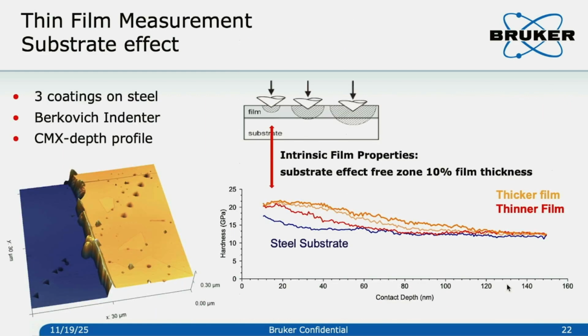So this is very important for us to understand when the substrate effect starts. So these are two examples with different films. You can see the yellow film: we start from almost 10 nanometers, and it's very stable until 40 nanometers. The hardness starts to drop, transferring to the substrate. Then the other film, I think, starts from almost 20 nanometers. So if you have no idea about your thin film sample, you need to use CMX first to understand when you are going to get the substrate effect. This is very important, right? So, of course, for yellow, I think the film is thicker. If we apply the 10% rule, the film thickness is around 400 nanometers.